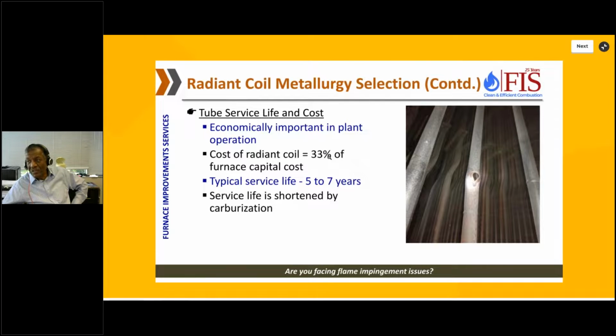Radiant coil generally in other heaters is only 10 to 15% of the furnace capital cost. Here it is 33%. And it only lasts 5 to 7 years. Generally we talk about 100,000 hours, which is about 12 years, for most of the other furnaces, but here we're talking of only 5 to 7 years. And the reason is because of carburization, the tubes can give way and we'll have to change the tubes.